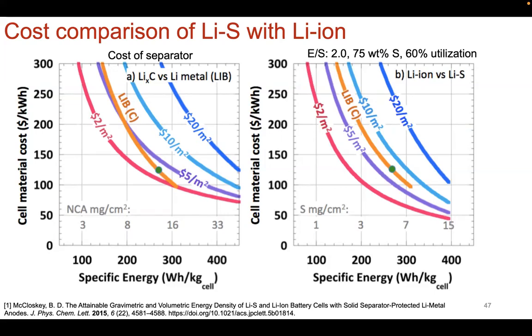Okay. In terms of comparing that with now lithium sulfur battery technology, you see here the same curve is applied for lithium-ion batteries with graphite anode. And what you see is, depending on the sulfur loading, between 1 and 15 milligrams per centimeter squared, if you want to achieve parity here, we're really looking at bringing the cost down to somewhere between $5 and $10 per meter squared of the separator, right? So that is achievable, but it's still pretty high. And that assumes these idealized numbers of electrolyte to sulfur ratio of just 2, so relatively lean, and 75% utilization. So the amount of sulfur that you put in and how much of the capacity you can get out is 75%. So 75% of what you actually put in terms of the electrode.